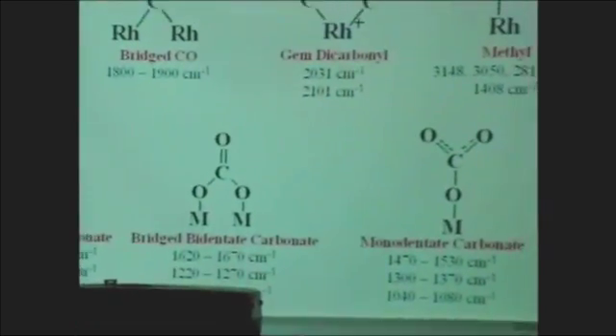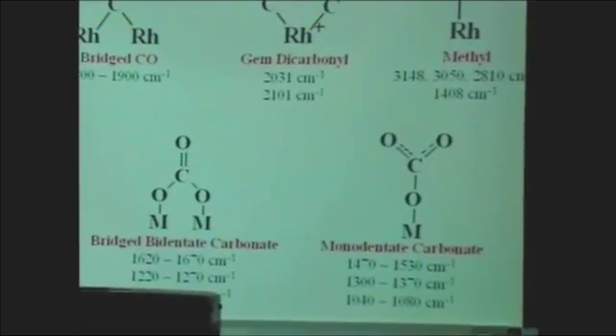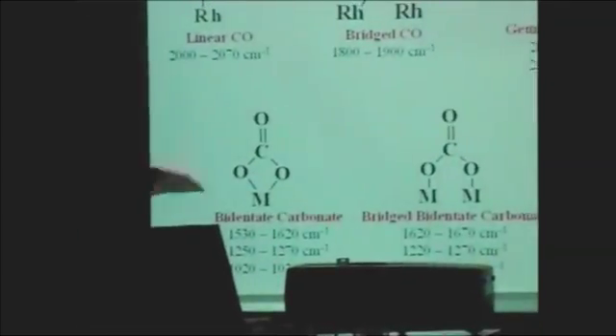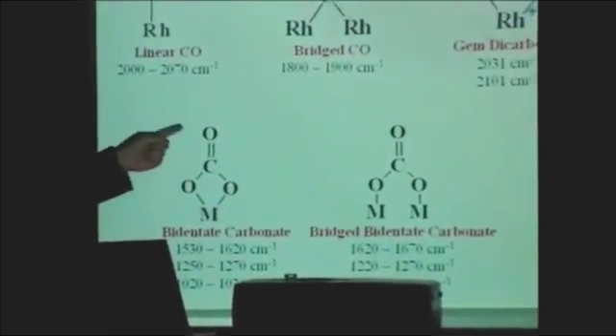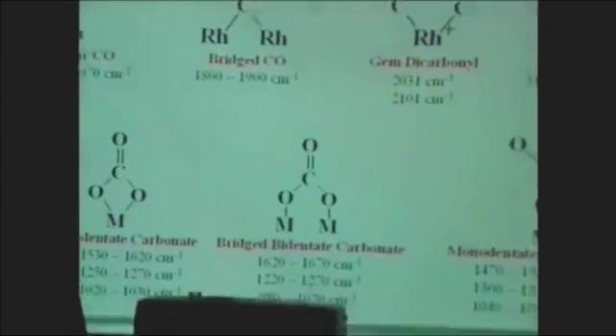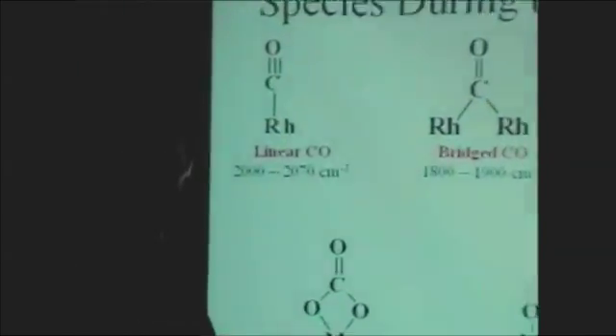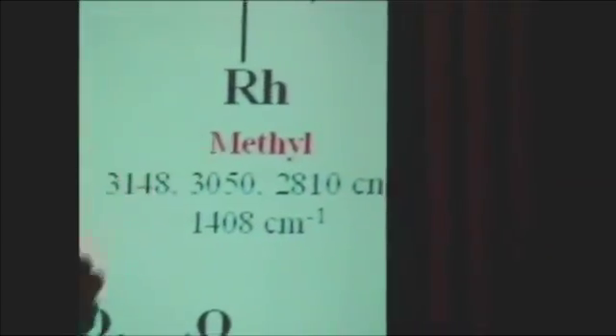form. And certainly carbon monoxide and carbon dioxide can adsorb on the catalytic surface. Most of the time, the carbon dioxide will adsorb on the oxide support surface to form various types of carbonate. Especially on ceria type oxide, CO2 can adsorb in various forms of carbonate. And hydrocarbon can also adsorb on the surface to form species like the methyl species on the rhodium surface.